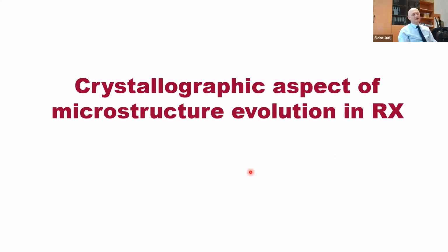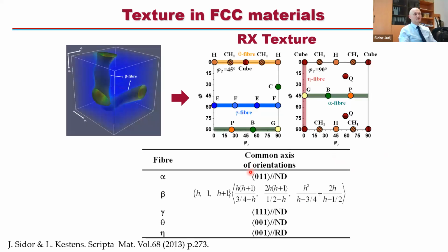Now, talking about the crystallographic aspect of microstructure evolution during recrystallization, you should know that in FCC materials, when they are subjected to rolling, a specific fiber tends to evolve. It's a complex-shaped fiber, what we call the beta fiber. It looks like this in Euler space, right? And for many years there was no precise description of this fiber, and almost 10 years ago, we managed to find the analytical description of this fiber, and basically by this massive formula, you can describe all components of this skeletal line which you observe in space.